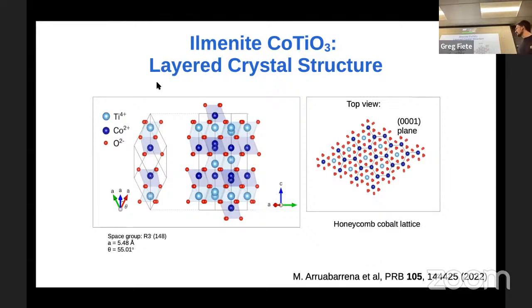And if we take a look at it, you can see that even though it's bulk, it has a very defined layered structure. And if we take a top look at it from the 0001 plane, we see how these cobalt atoms form a honeycomb, graphene-like sublattice, to say it in some way, which is the origin of having the topological or Dirac-like magnons.